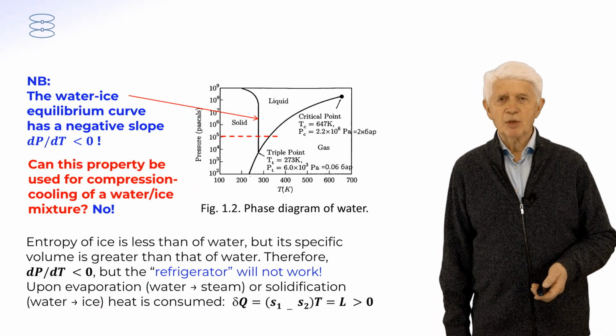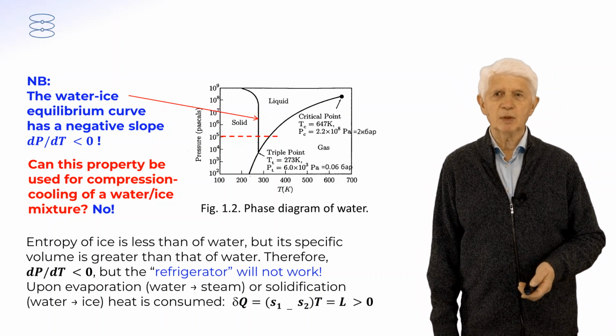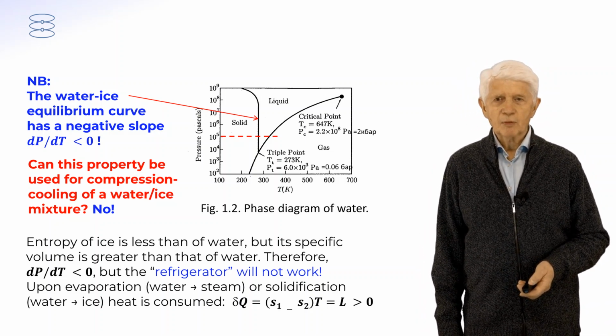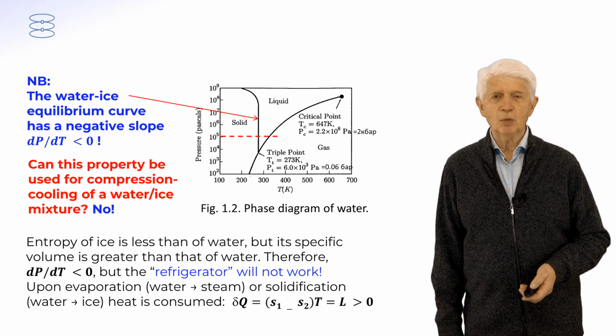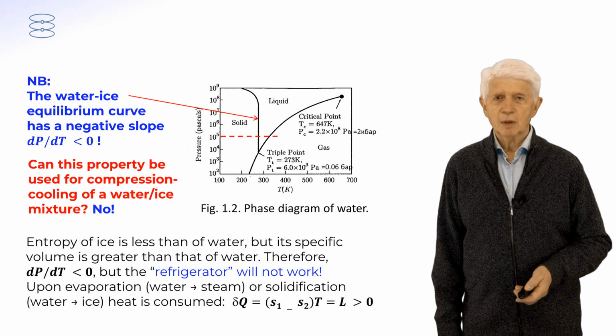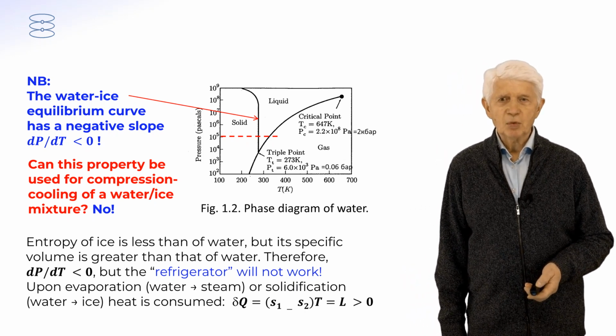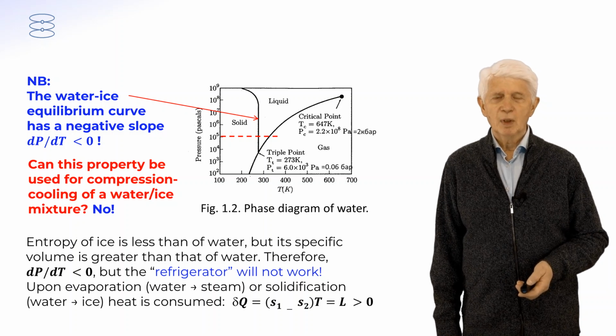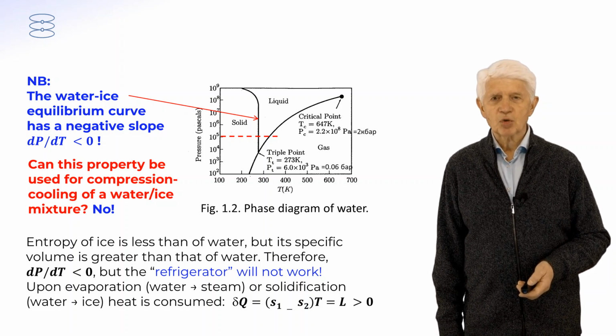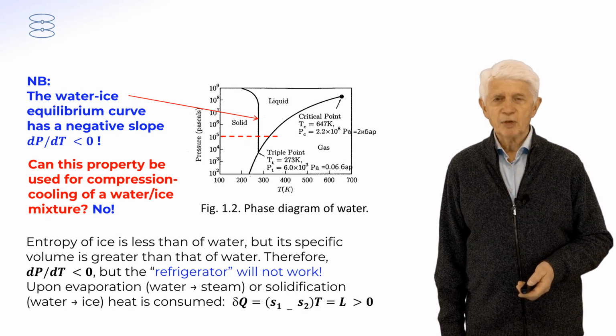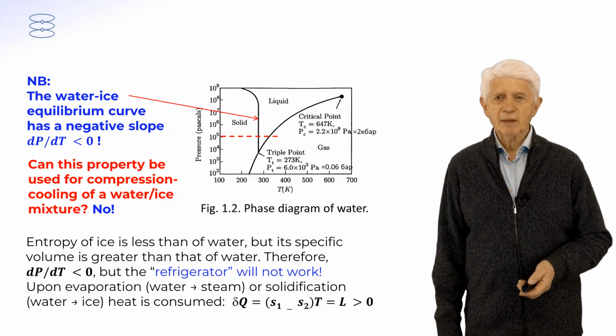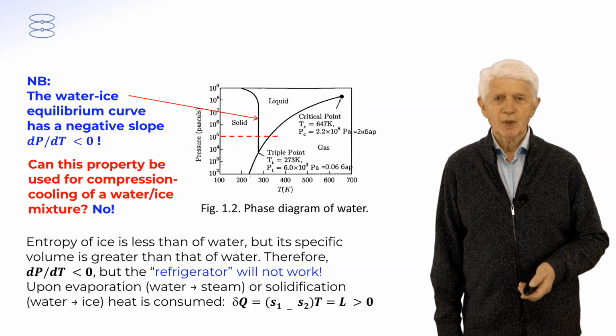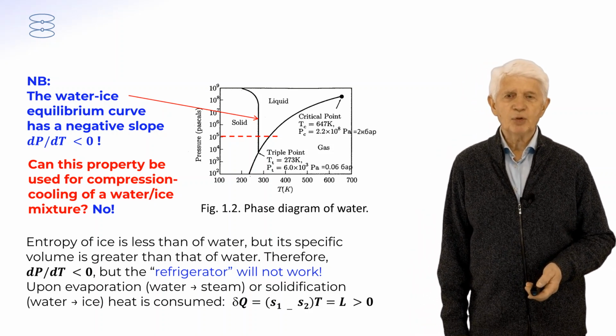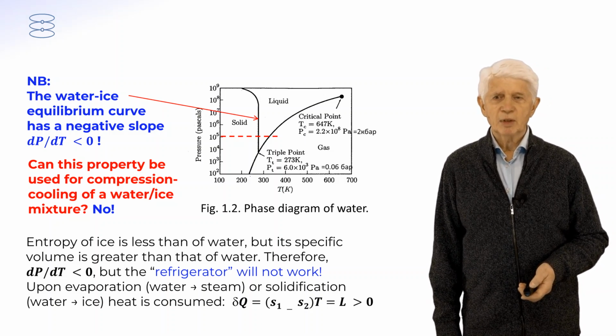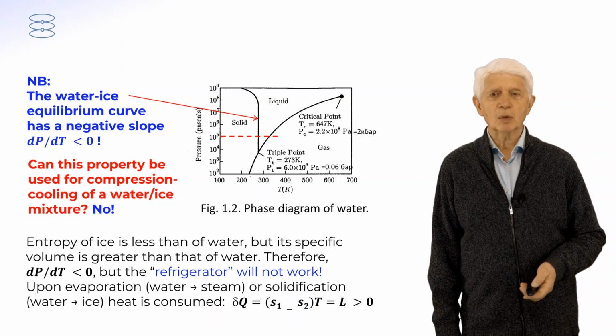Now let's turn our attention to the left border between solid and liquid. This curve surprisingly has a negative slope. dP over dT is negative. Can this property be used for compression cooling of a water-ice mixture? It seems that we apply pressure and should go down in temperature, like in a refrigerator, but it doesn't work, because the entropy of ice is less than the entropy of water, but the specific volume is greater than that of water. You remember that ice floats in water. Therefore, dP over dT is negative, but the refrigerator effect will not work.